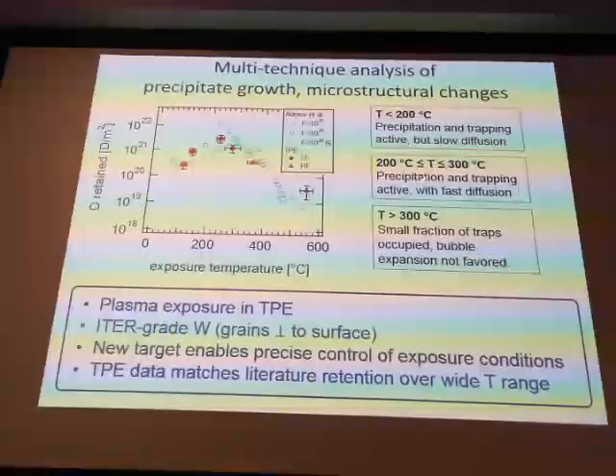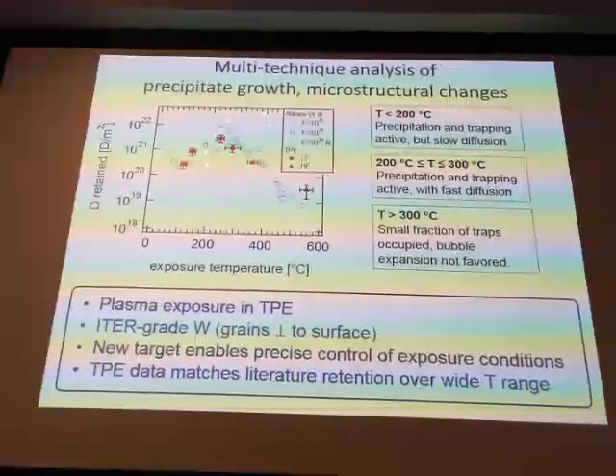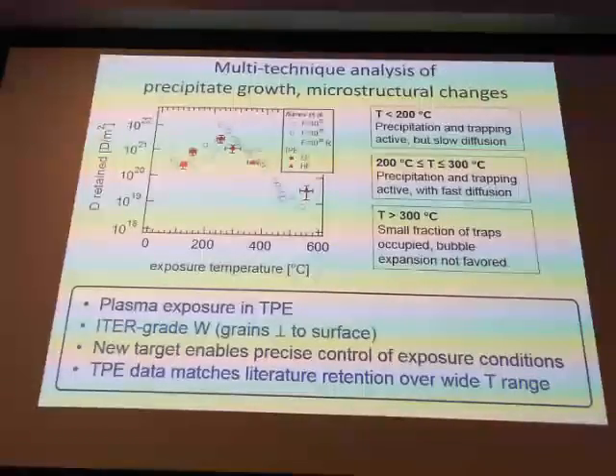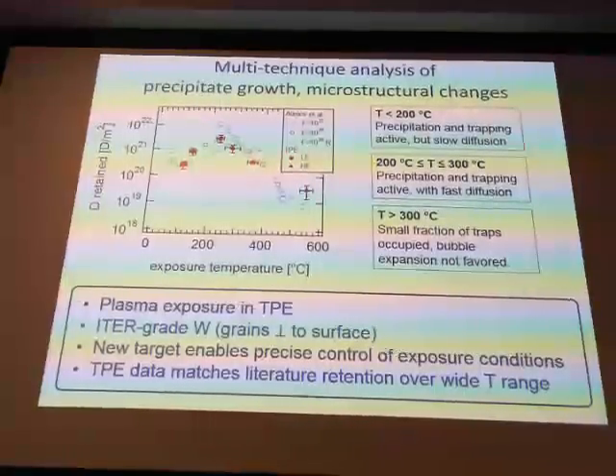Then at intermediate temperatures, you have relatively faster diffusion, and precipitation and trapping are still active. So you get the peak in retention here at, say, 200 to 300 degrees C. And then at larger temperatures, diffusion is very fast, but now the traps aren't as active anymore, and so the tritium retention in tungsten goes down thereafter.